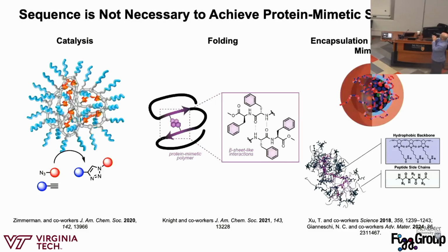So Ting Xu was a large inspiration for this work. This figure is essentially showing a protein surface where instead of looking specifically at the chemical interactions on the surface, they zoomed out a little bit and looked at big patches on the protein surface and said, okay, this big patch is cationic, this big patch is hydrophobic. Can we design a large polymer that can essentially engulf this protein, where we don't need sequence specificity because we're relying on a length scale that's removed from exact interactions on the surface, more like average interactions on the surface? So this is the Science paper.